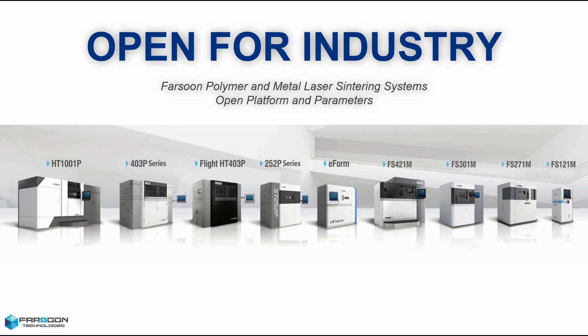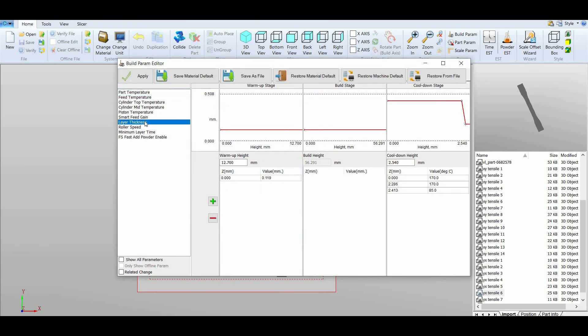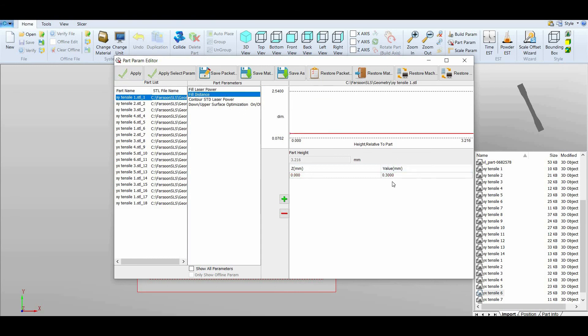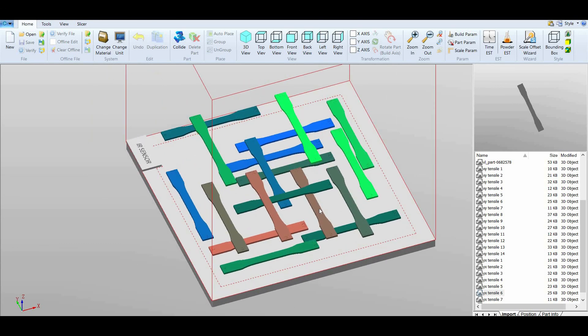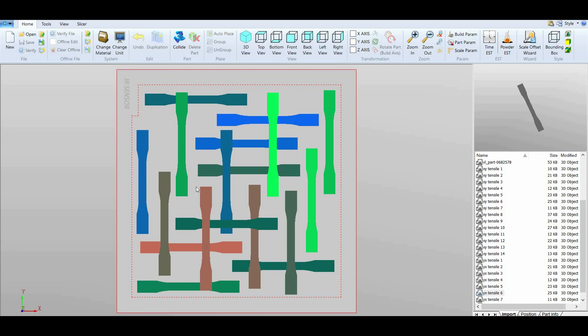With Farsoon's open platform and parameters philosophy, users are able to create individual material parameter sets, including the parameters outlined in this video, and alter them freely pre-build or during the sintering process. So now that we have our ED value for our PA3300, we're going to set up and run a build to verify we're getting the mechanical properties that we need. We'll set our layer thickness to 0.12 millimeters under build parameters, then set our fill laser power to 72 watts and fill distance to 0.3 under part parameters. I've set up a build about two and a half inches tall, filled with XY and YX tensile bars spread across the part bed — at the corners, sides, and in the middle — to ensure a uniform mechanical property value throughout the whole build.